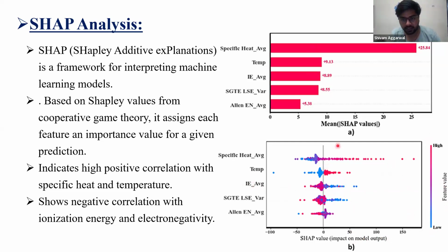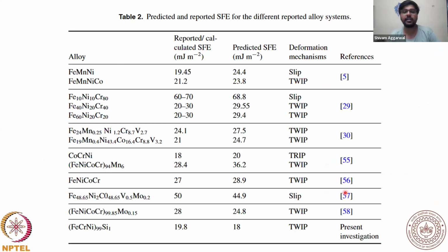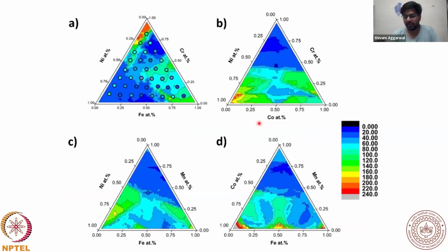And in this plot, you can get those in detail. This is the predicted and reported values which they compare, and they are approximately the same. There is some error of about 20% or 25%, which is acceptable. And in this plot they show how they get the SFE value if they make a ternary compound, like chromium percentage, cobalt percentage, and nickel atomic percentage. If I go to this point, how do I get the stacking fault energy?